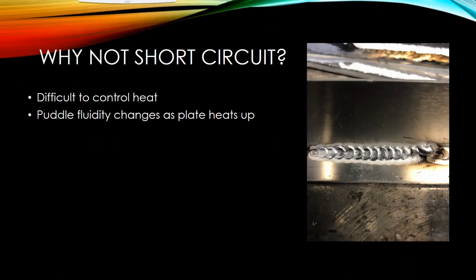One process that you'll see not used very often with aluminum is short circuit transfer, and I just want to lightly touch on this. I did a little sample weld this morning just to show what can happen when you're running short circuit. On aluminum, it can be very difficult to control your heat. Looking at that picture on the right, you can see right at the start, it's very cold and it roped up right on top of the plate. It didn't wash out at all, and there's probably no penetration into the plate. Not too far into the weld, you can see that it does start to wash out and it looks pretty nice. But because it's so difficult to control that heat in aluminum, if we were to keep going down that plate with that weld, it'd probably burn through in another inch or so.